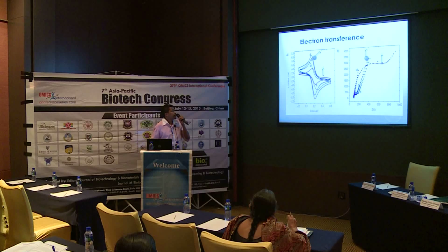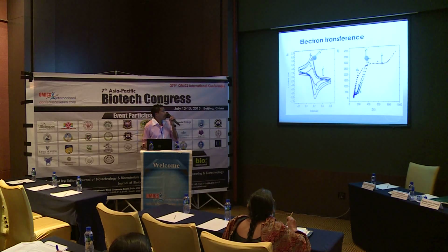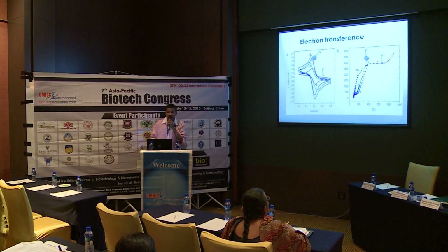This is the left one, some curve we made to see the conductivity. As you can see there, the glassy carbon electrode, when covered with multiwalled carbon nanotube, the sensitivity is increasing, so you should test it before. And when not using the carbon nanotube it is the lowest, as you can see, the pink one.